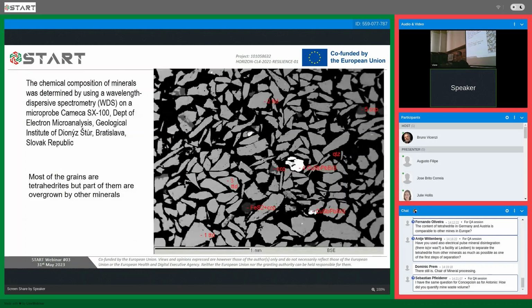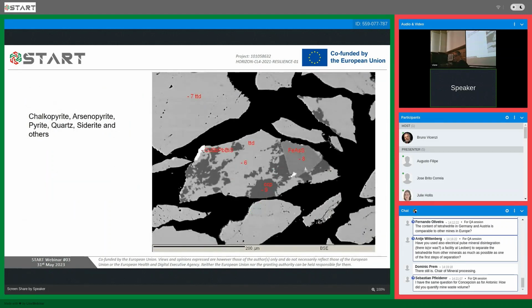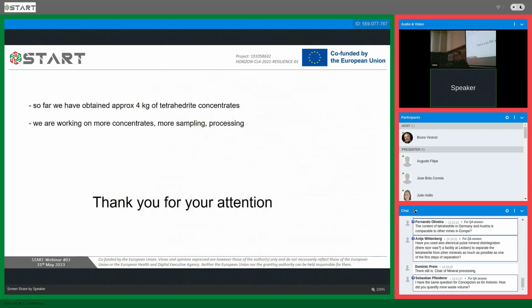The chemical composition of minerals was determined using wavelength dispersive spectrometry on a Cameca SX100 microprobe in our Department of Electron Microanalysis at our institute in Bratislava, Slovakia. Most of the grains in concentrates were tetrahedrites, but part of them are overgrown by other minerals. For example, this one grain consists of tetrahedrite, but also chalcopyrite, arsenopyrite, pyrite, quartz, siderite. So it's not possible to separate it 100%. So far, we have obtained approximately 4 kilos of tetrahedrite concentrates.